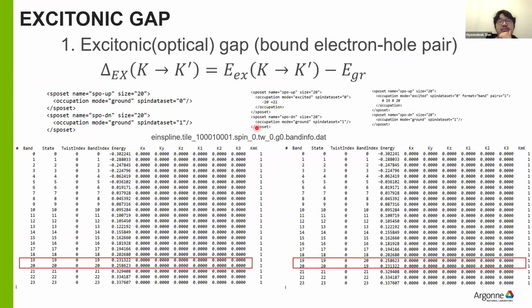So to calculate the excitonic gaps, we need to calculate the energy difference between the ground state energy and the energy from promoting the electrons from the valence band to the conduction band. Let us suppose we just need to calculate the direct gap at the gamma point, as we showed in the band structures for the bulk systems. So we will start with the basic one by one cell and calculate from there. We need to calculate the direct gap at the gamma point.